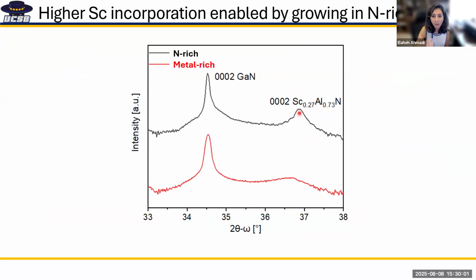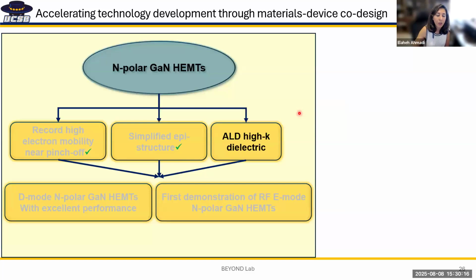So that's so far the work we've been doing on scandium nitride. We've been studying the growth space for this material. And now our plan is to use this also as a barrier, both in gallium polar and nitrogen polar HEMTs. So far, what I have talked about is that we demonstrated record high electron mobility near pinch off, and we have simplified the epi structure. Basically, you didn't see any of all those grading and silicon doping and all that.